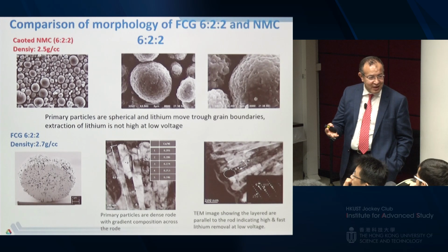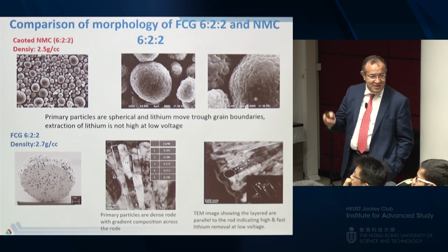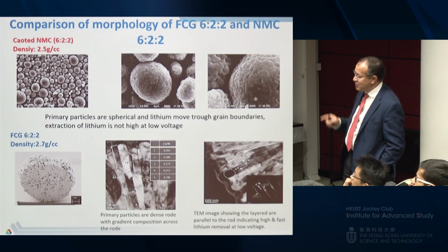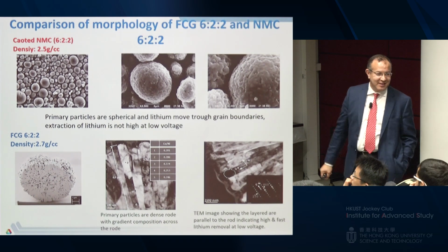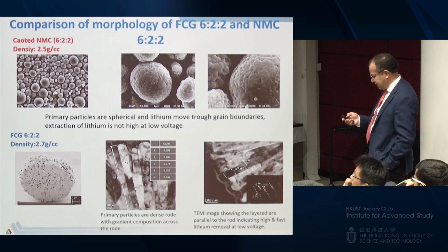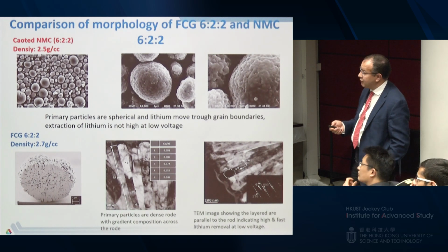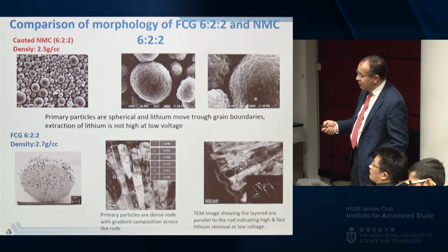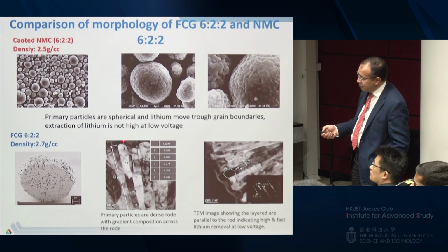Because you pack more active material in the electrode, keyword. The energy is capacity, voltage, and density. Remember that. If you use a nanomaterial, then you drop your density significantly, and therefore your capacity at the electrode level significantly as well. The other thing we've seen is that the gradient approach is also at the primary particle.